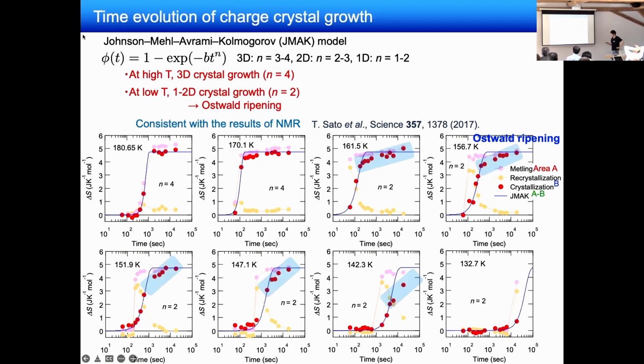And here is a result of the DSC measurement. These figures show the entropy change as a function of time measured at various temperatures. Actually, these results show that the charge crystallization progress can be given by this JMAK model, shown by this blue line. I won't explain the details, but these results are very consistent with the results of NMR performed by another group.